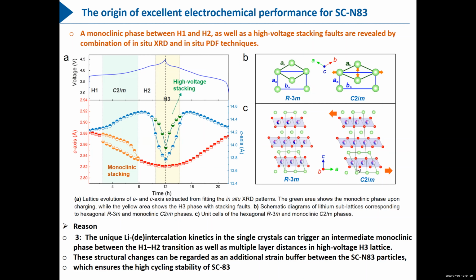Currently I am still working on this project to find the reason why this happens in the single crystal materials. But your single crystal nickel-rich sample has the same composition as the polycrystalline one, right? The only difference is the size. Yeah, the composition should be the same. So it's very strange. Normally for NCM materials the order-disorder transition is not very common, because nickel and manganese help cobalt to eliminate the order-disorder transition.